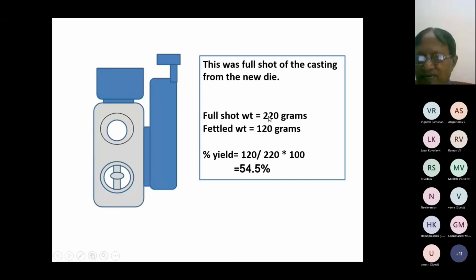Shot weight was 220 grams, and fettled weight was 120 grams, and yield has gone up very well from 35% to 51%. Sawing was also quite easy. You can just cut it off on this one. This was not without problems. We had some problems in this area.